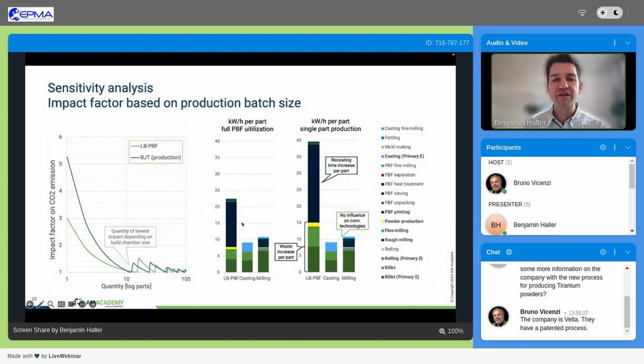And here on the right side, you can see how this splits up between the green bar, which is the material, and the dark blue, which is the printing of the part itself. You can see that if you produce a single part in the build job with powder bed fusion, you have almost twice as high CO2 emissions in this example as with better utilization. This always depends on how well you can actually utilize it.